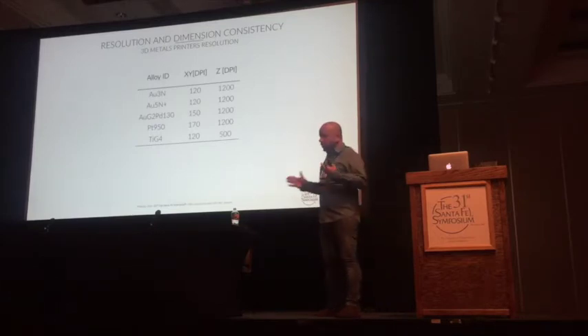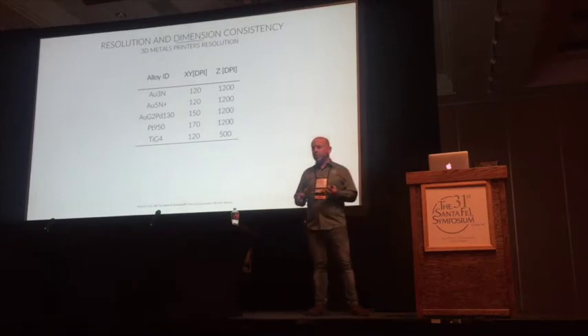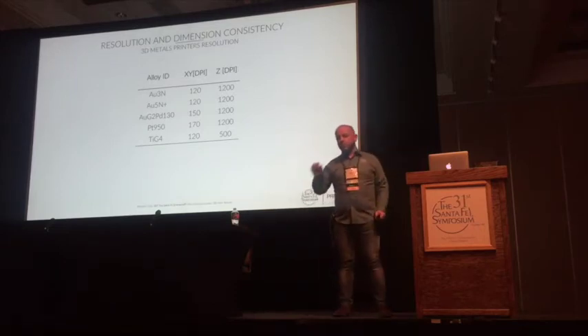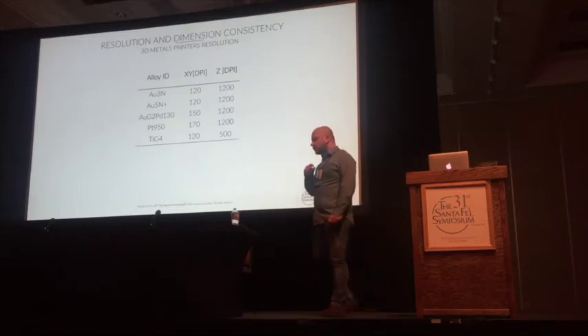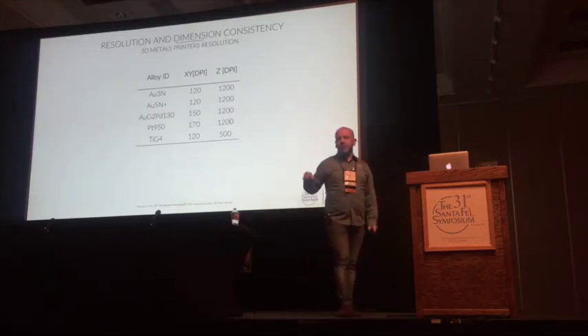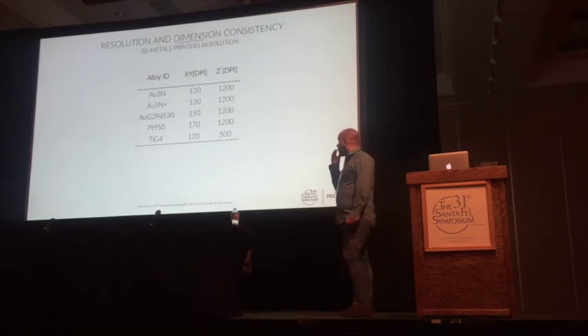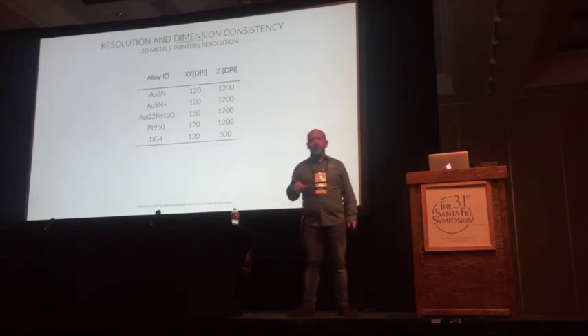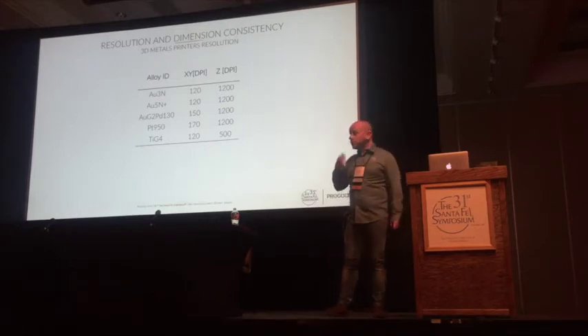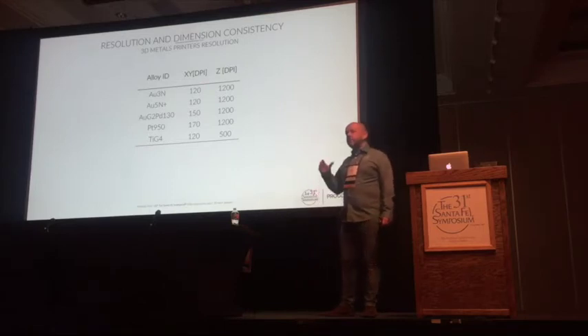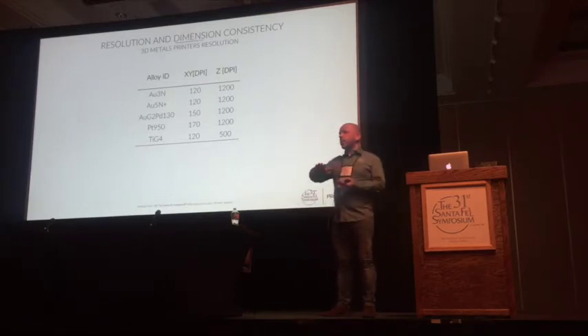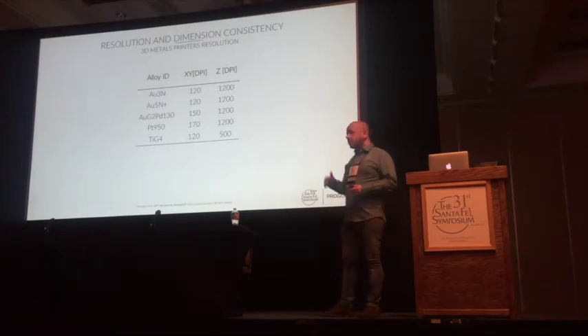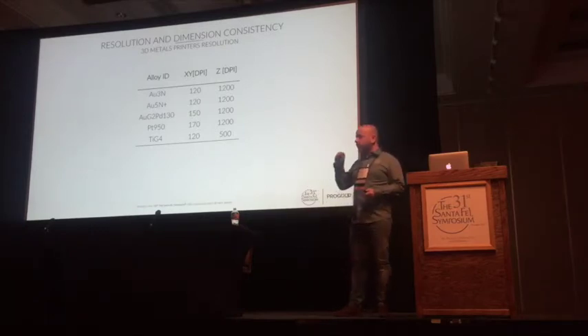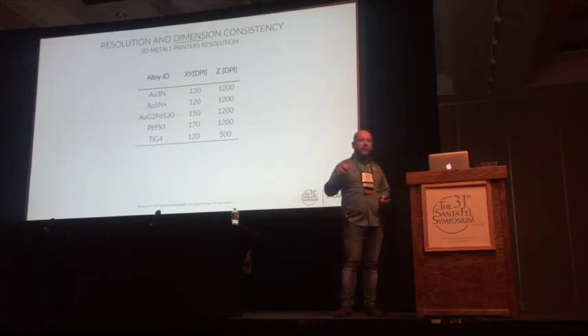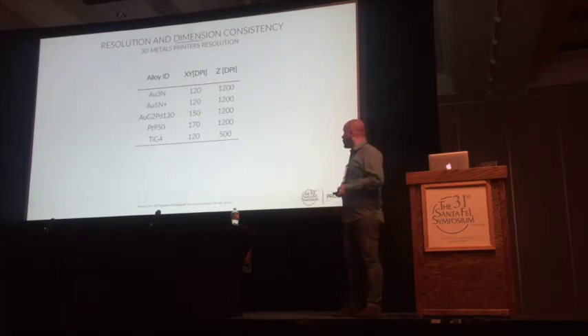Here I put the resolution. I was not talking about the resolution of printers, but about layer thickness, spot size, melting trace thickness, vector thickness. Here I just put the XY resolution. In the case of gold it is something like 120 dots per inch, and in the case of platinum it is a bit more on an XY plane. In the case of Z, we are much more resolute because we are able to build parts at 20 microns. So the resolution is quite okay on the Z axis.